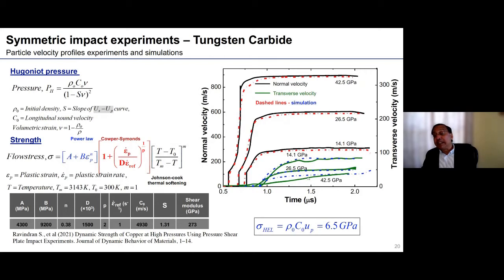I want to emphasize that having this transverse response not only gives you the strength model. Obviously, people use strength models even when modeling just normal plate impact experiments, the shock experiments. There, in some sense, the plasticity parameters, or the strength parameters, are unconstrained. They're not so well constrained. When you have transverse velocity measurements together with the normal velocity measurements, then this is a highly constrained problem. So we can get a very good representation of this material model. So we are confident that we have a very good material model for the tungsten carbide here.